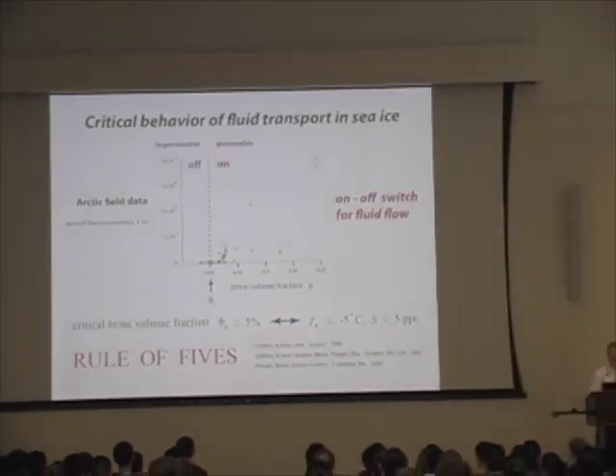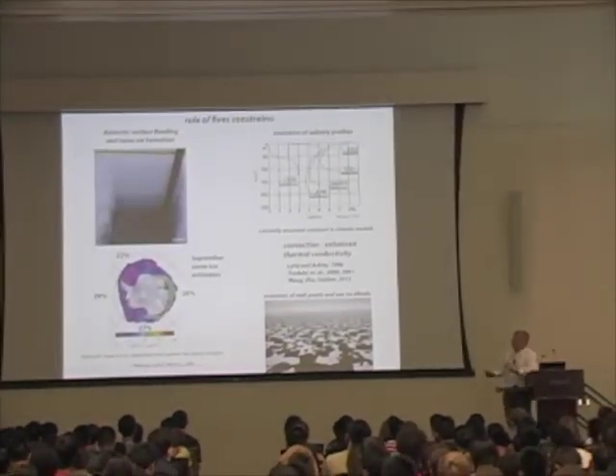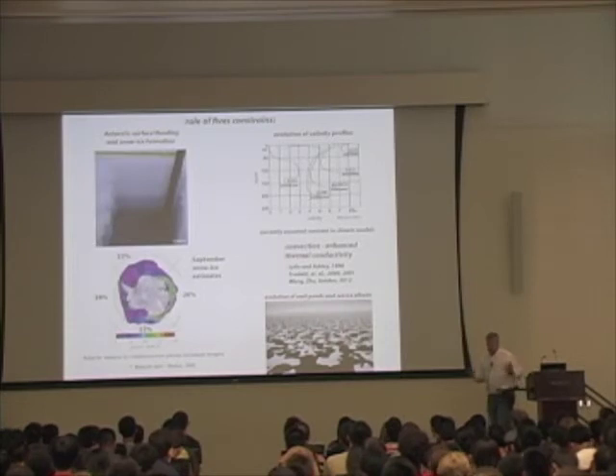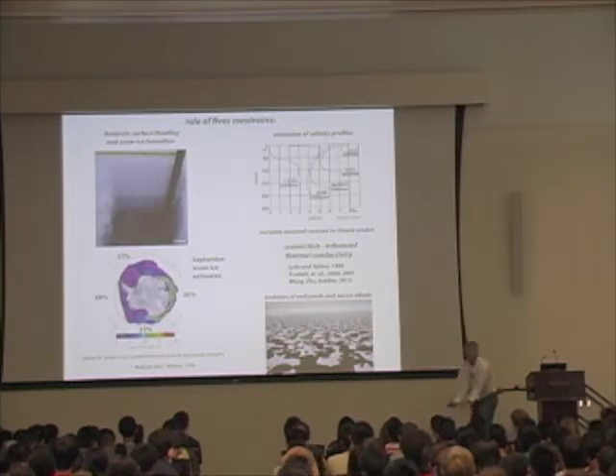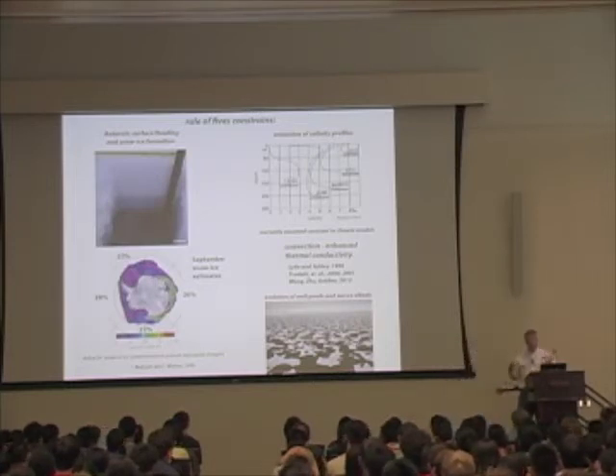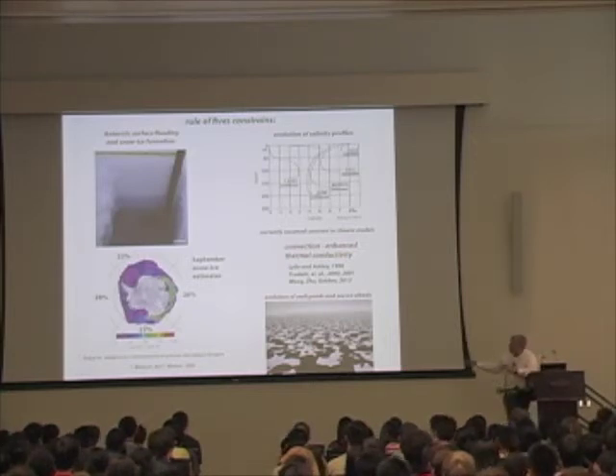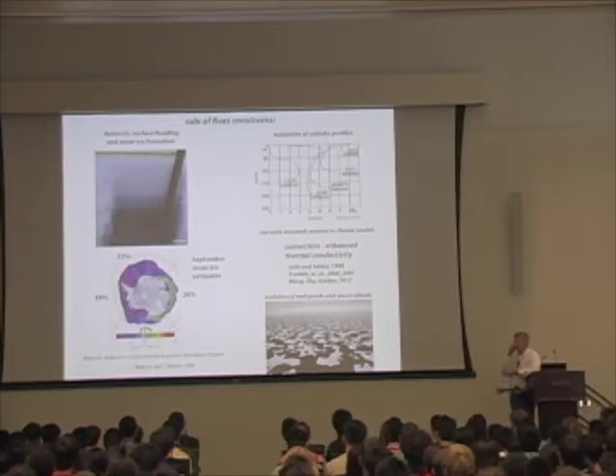And it controls a lot. In fact, I discovered it by being out in the middle of a storm in the Antarctic at midnight in 60 knot winds, and I actually witnessed seawater percolating up and flooding the surface. That was what gave me the first idea about this phenomenon. And in fact, the freezing of that slushy mix on the surface of Antarctic sea ice accounts for about 25% of the ice that's produced in the Antarctic. So it's a very important process.